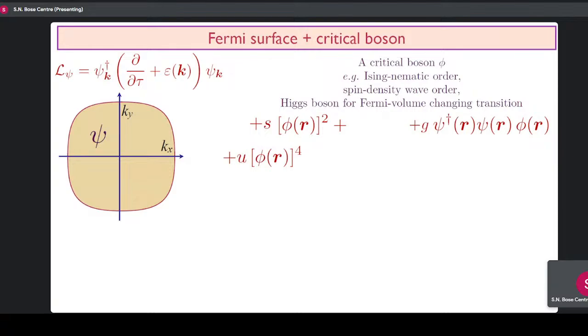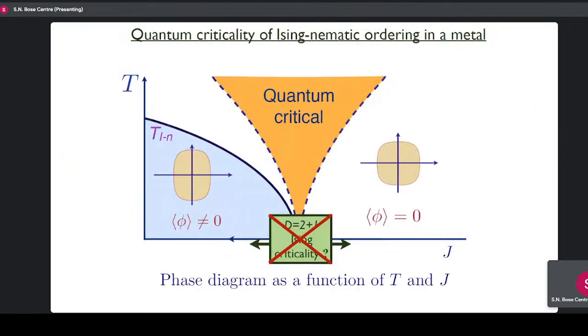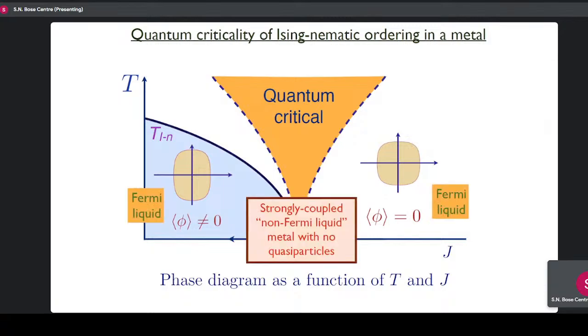And the fact that this Fermi surface is important was pointed out by Hertz, I guess sometime in the 70s, in a famous article on quantum phase transitions. Okay, so this is the theory you have to study. And since the time of Hertz, this theory has been studied a lot, and it's pretty well understood. So what we know now is that this point here is what we call a non-Fermi liquid. It's a state of matter where the Fermi surface is well defined. It's still a very sharp Fermi surface, but the quasi-particles are very short-lived. There are no quasi-particles at all. So this is a strange object which I don't have time to explain because it won't be that crucial for what I have to talk about. Anyway, so this is now fairly well understood that there's a new phase of matter here, which we call a non-Fermi liquid.